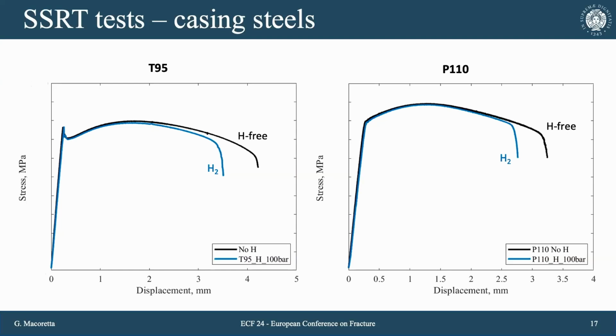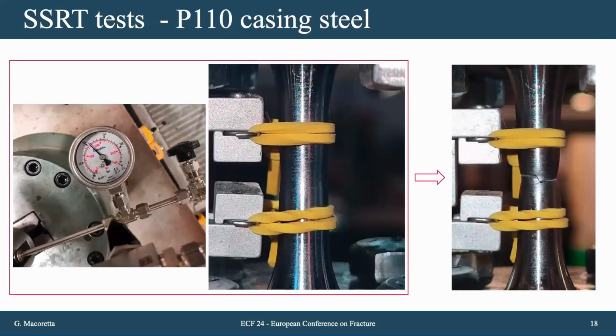And so the effect of hydrogen in this material too is a ductility reduction without a reduction in the material strength. We can see that even when we have necking, we still keep the pressure inside the specimen. So we have a pressure drop only when we reach failure. Until failure, we have a continuous section that can still keep the internal pressure.